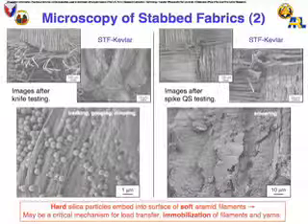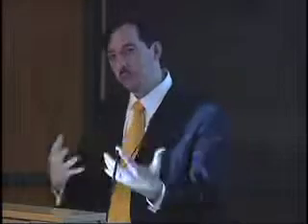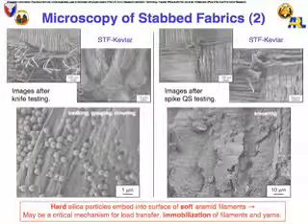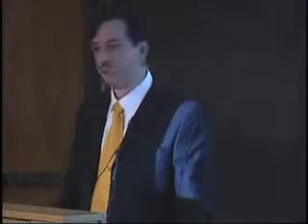And these are a piece of the Kevlar, which is normally smooth, the individual filaments, is now grooved. And you can see how the particles have grabbed a hold of the fabric to prevent it from moving and preventing things from penetrating through. And you can see over here how the material's been plastically deformed. DuPont didn't believe this at first, that the Kevlar could actually be plastically deformed. So we're able to really absorb the energy, deforming the target, breaking particles and things, rather than the person behind it. And that's the goal.